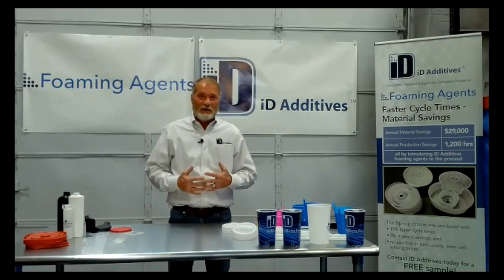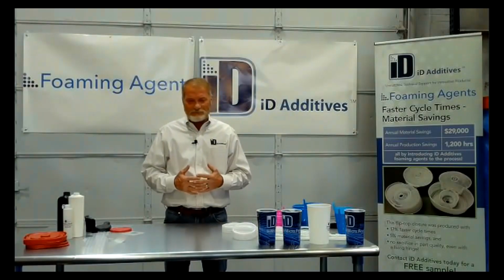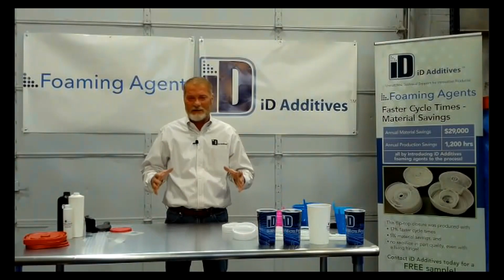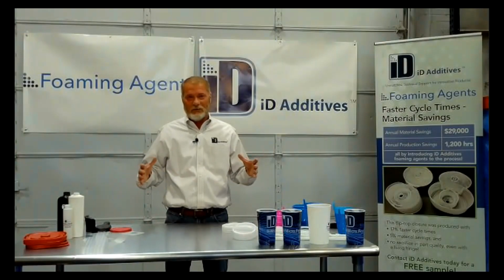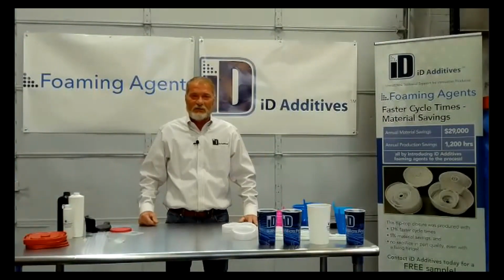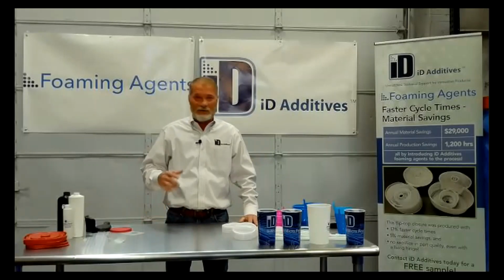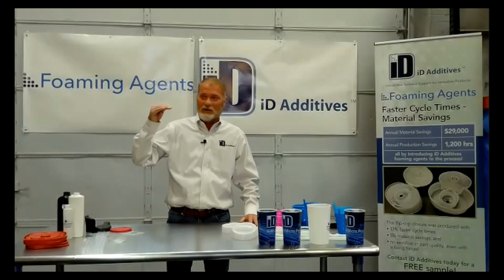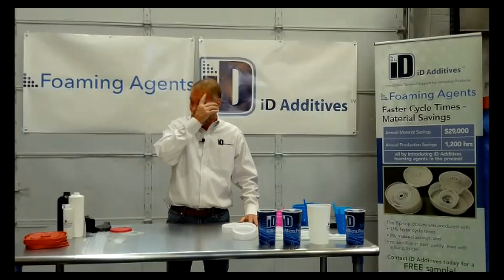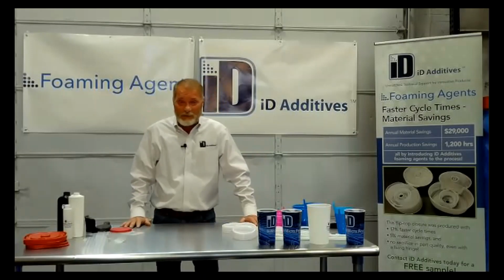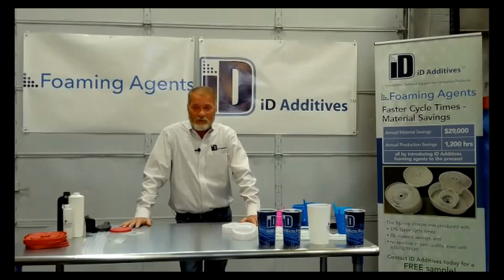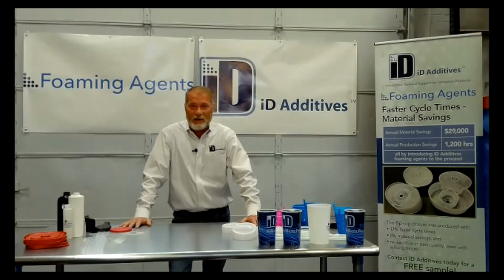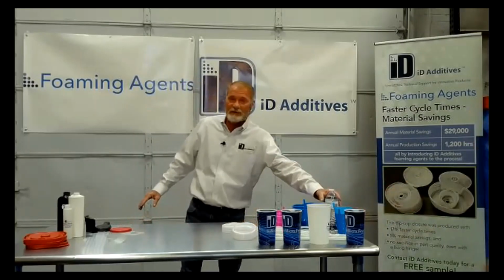I've done PET pipe. I'm not PET pipe, but polyethylene pipe. Foamed it, looked great. They did a burst test. Well, the burst test didn't hold up very well. I mean, it held pretty good pressure, but it never reached what they typically do. So that didn't go over so well with them. But the more foam you put in anything, it's an additive. So the more foam you put in, the more you might affect the structural integrity of the part.